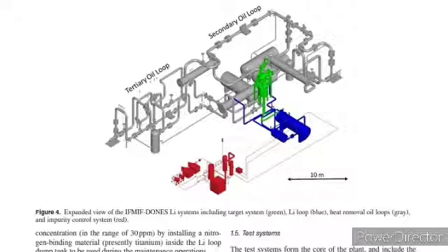The purification branch contains a cold trap to remove elements with temperature-sensitive solubility in lithium, mainly CO and metallic impurities, mostly related to corrosion and activation products as binary or ternary compounds, and the hydrogen trap to remove hydrogen isotopes by chemical reaction with a hydrogen binding material present.